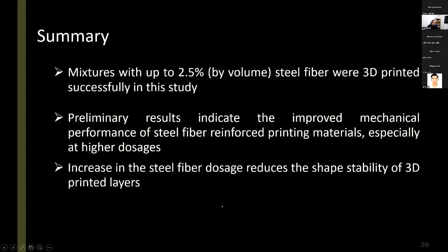I think I'm almost out of time, so a quick summary of our project on steel fiber reinforced materials. We were able to print mixtures with up to 2.5% steel fiber with some level of layer deformations. We are already seeing significant improvements in the mechanical performance of 3D printed materials with these steel fibers, especially when the dosages are higher, at 2% and 2.5%.